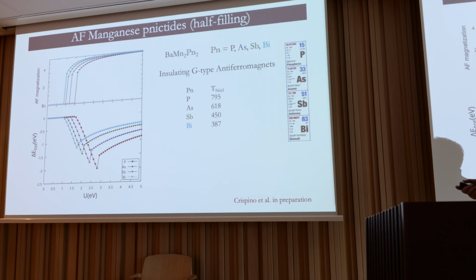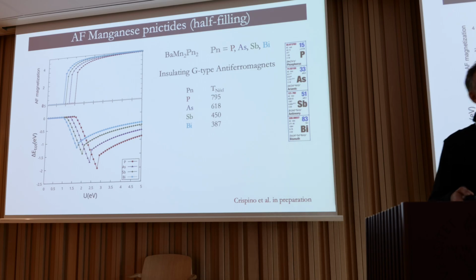You can find that these are antiferromagnetic insulators and have Néel temperatures exactly in the order of the series here. From phosphorus down to bismuth, you go from 795, 618, and so on in this order. So we did our calculations just to estimate if these are in an itinerant picture of itinerant magnetism.